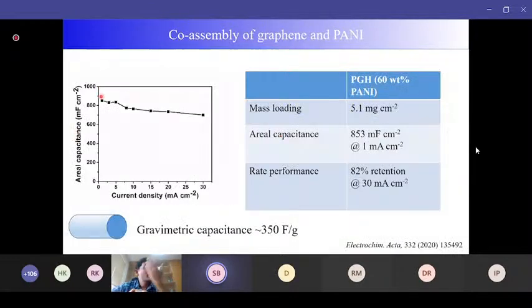And as you can see, previously the performance was around 33 millifarad per centimeter square, but right now the areal capacitance we can increase to more than 800 millifarad per centimeter square because of the presence of this polyaniline structure. In this case, the areal capacitance is around 853 millifarad per centimeter square, and it also retains the performance at a very high charging and discharging rate.